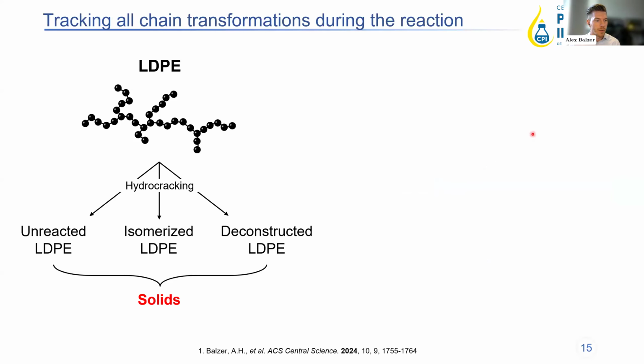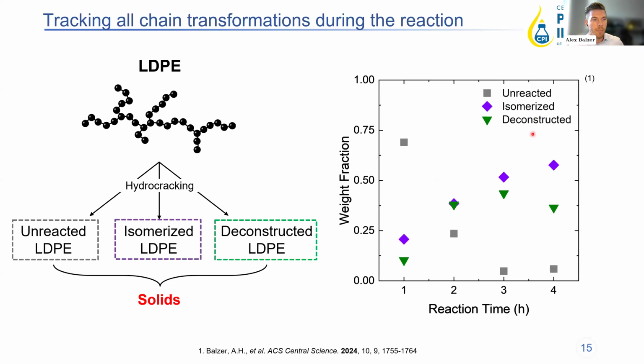But from this, we basically were able to identify our intact yield, our reacted yield. So we have three equations with three unknowns. We solve a mass balance to back out the fractions of unreacted, isomerized, and deconstructed chains throughout this hydrocracking. And I'll just point out that even at the longest reaction times of 4 hours, we still have unreacted chains inside of these solid yields. So that means that there are still chains that haven't even interacted with the catalyst, even though you can still see on a mass balance an 80% drop in mass of your solids.